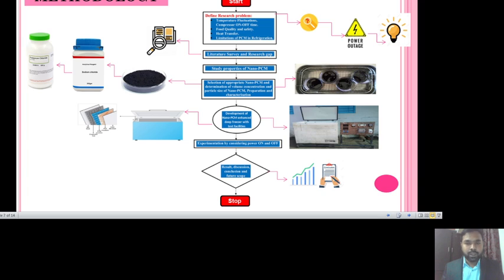So in order to mix the graphene oxide nanoparticle with the phase change material, we are using an ultrasonic agitator. It is available in our laboratory. We keep the Nano PCM mixture at about 70 to 80 degrees centigrade for 3 hours, and after mixing we will get the Nano PCM combination. After that, we start to manufacture the experimental setup by studying all properties, and after mixing the Nano PCM.